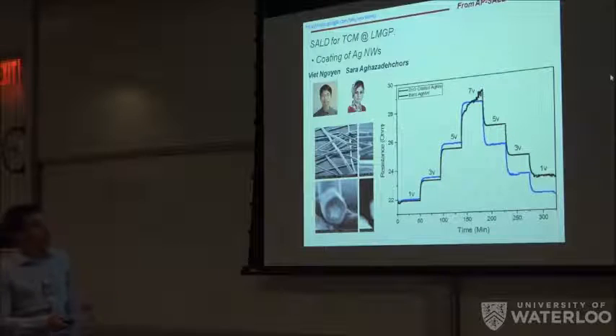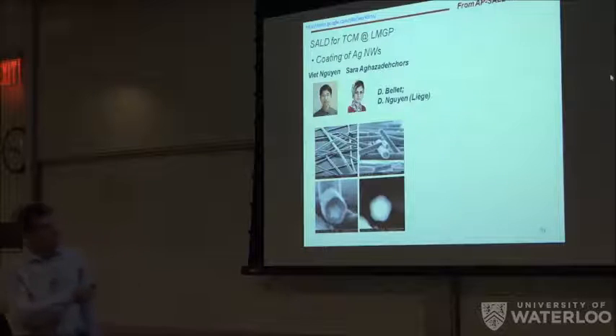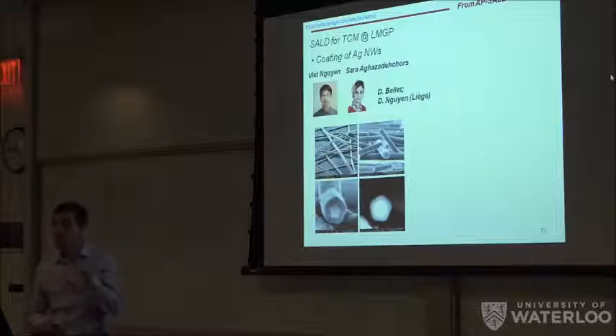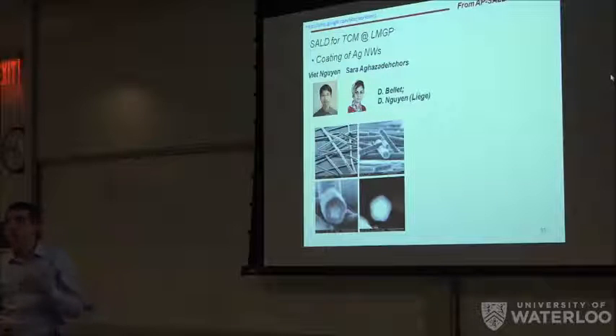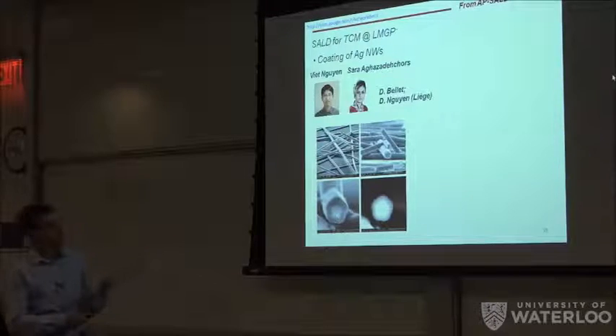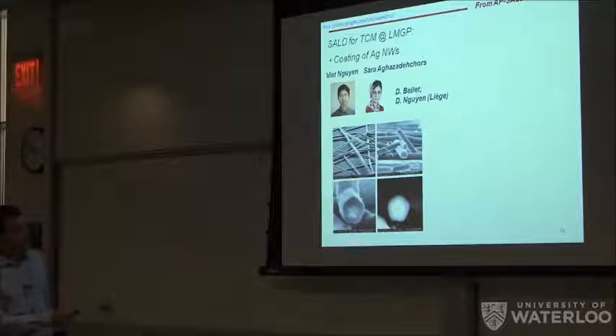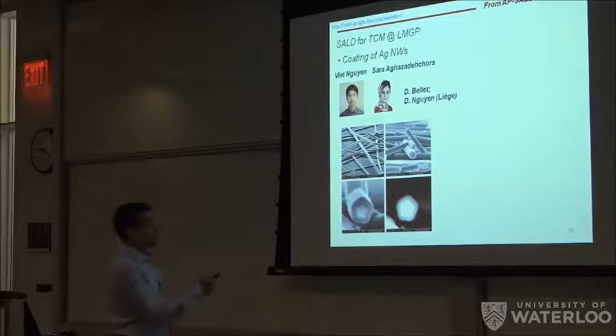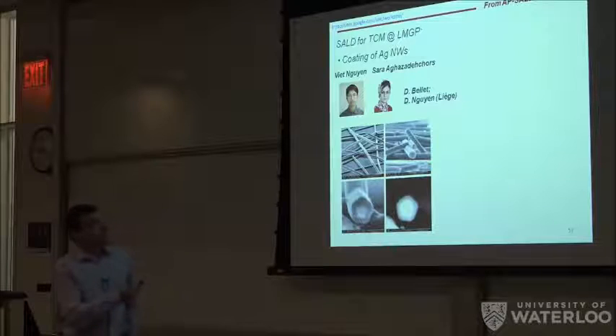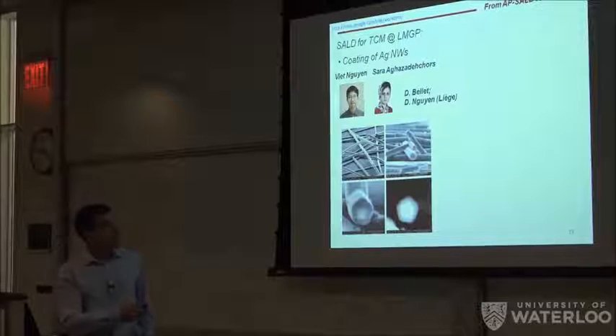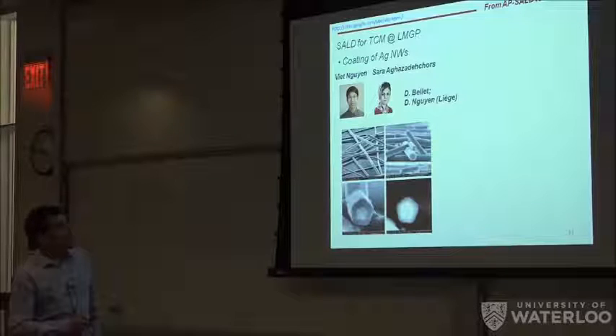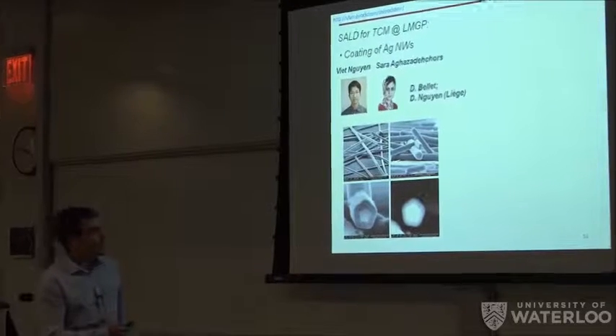So what we're trying to do is to protect these networks with a thin layer of oxide to try to enhance its stability to thermal and electrical annealing. You can see here we made a thicker coating just to be able to image it, but normally we work with 6, 7 nanometers. In this case, it's around 30. And you can see that, again, the coating is really conformal, homogeneous, very nice. And this is research work that is done in collaboration with D. Nguyen in Liège, and mainly done by Sara Aghazadehchors. I hope I say it right.